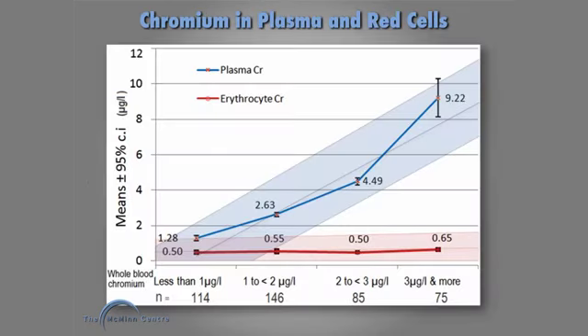Now, this is some proof that chromium 3 doesn't enter cells. This is a group of people with metal-metal hips, and their whole blood chromium has been broken down into less than 1 microgram per mil, 1 to 2, 2 to 3, and 3 to 4. And on concurrent specimens, my lab folks have measured the red cell chromium, the erythrocyte chromium, and the plasma chromium. And you can see that as the plasma chromium increases, there is no increase in the red cell chromium.